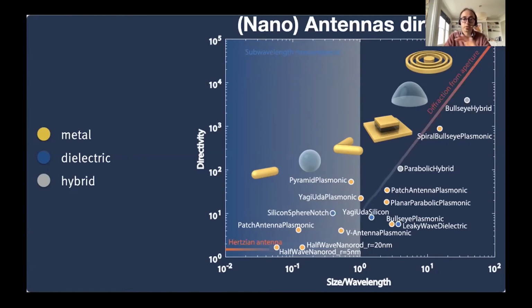And there you see that we have many different designs, metallic, dielectric, hybrid, and they all have quite a good directivity, of the order of 100 to 1,000. And so you see, there are ways that we can extract the light very well from an emitter by using this nano antenna. Okay, now I can put everything together.